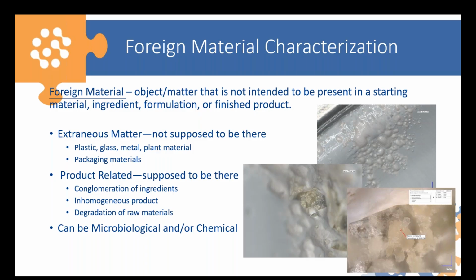And so when we took a closer look at these cans, especially the ones with the failures, what we found was that the lining was not sealing properly to the can around the lip of the can. And so what was happening is as these were being stored or transported, some of that brine was leaking between the can wall material and the lining. And then the brine was getting in there and forming these crystal deposits, resulting in these blisters. Based on this, the client could go back, fix this problem, improve their cans, and prevent this from reoccurring. So this was a combination of a foreign material characterization and a packaging failure analysis. And this was a case where the foreign material was technically product related, it was the brine, but it was in a place, in a form where it shouldn't be.